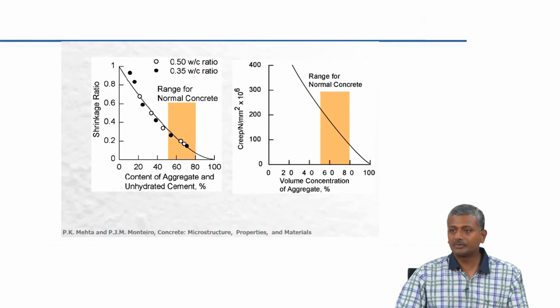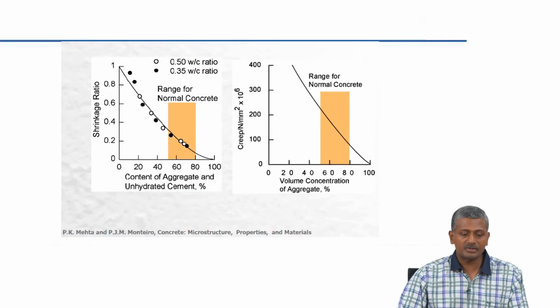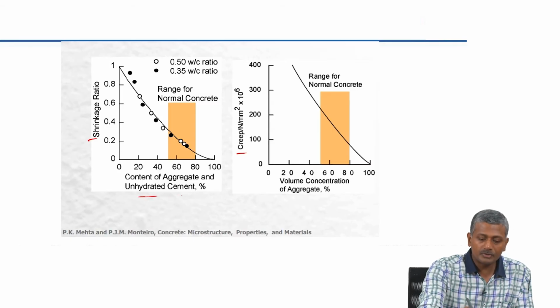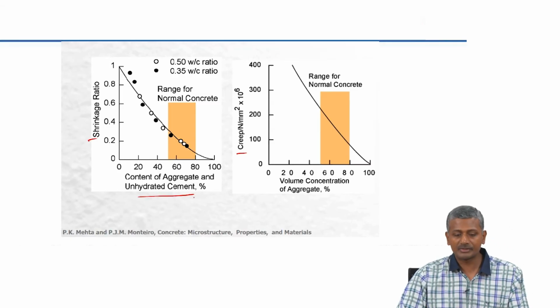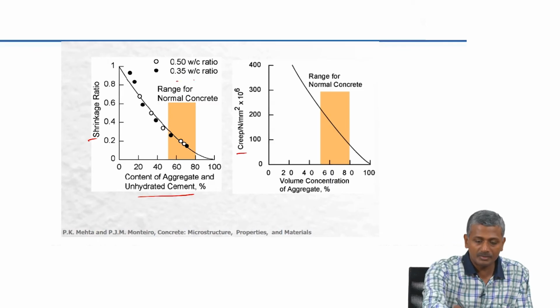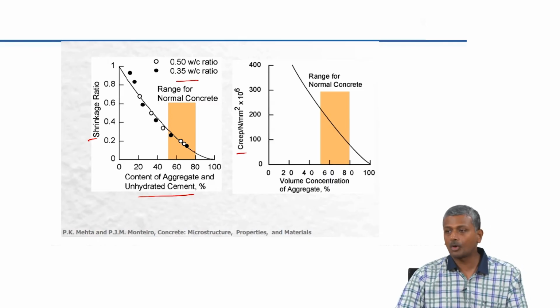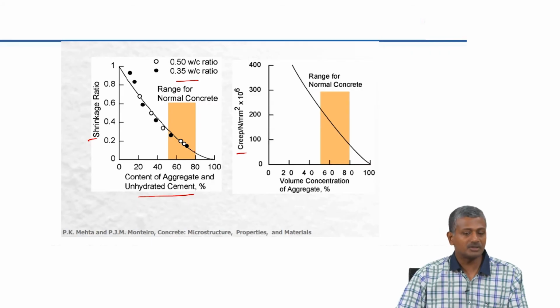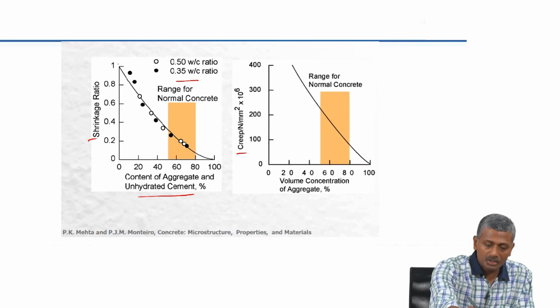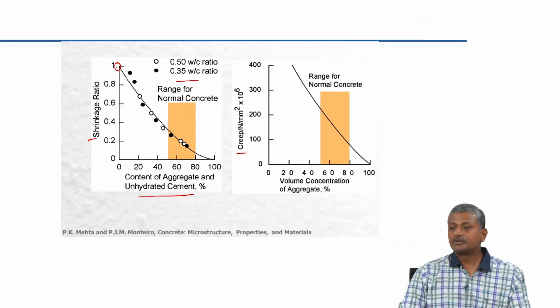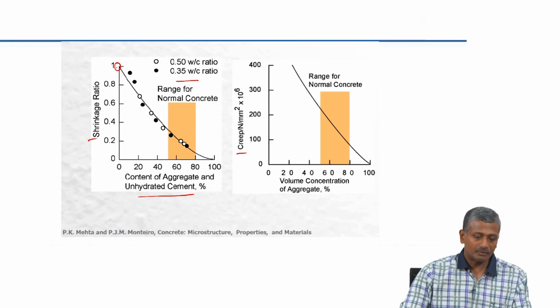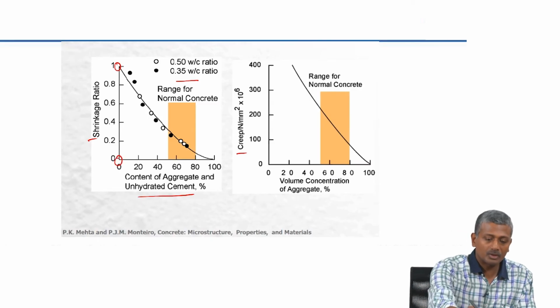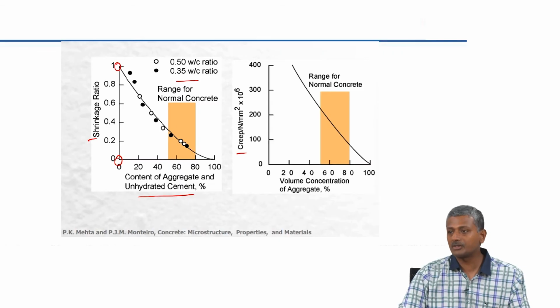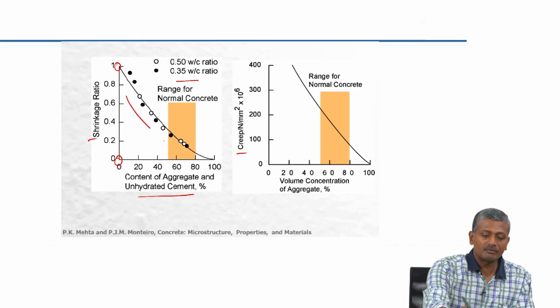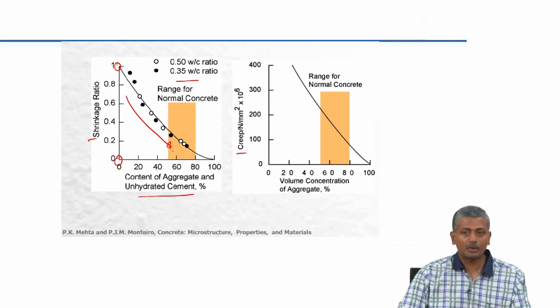So, this is data from your Mehta and Monteiro book, which plots the shrinkage and creep in terms of the content of aggregate and unhydrated cement in your system. You can clearly see for different water cement ratios, you can see a major drop in your creep coefficient as well as your shrinkage ratio that you get in the system. So, here shrinkage ratio is the ratio of the shrinkage of concrete to shrinkage of paste. So, obviously, when there is no aggregate in the system, your ratio is 1, that means you are getting shrinkage of paste. As you increase the extent of aggregate in the paste, the shrinkage drops drastically.